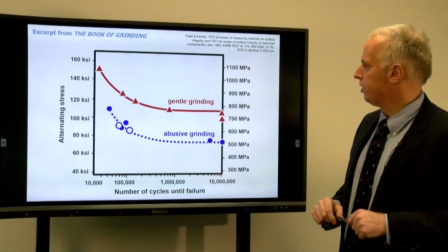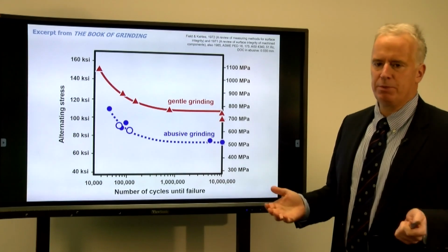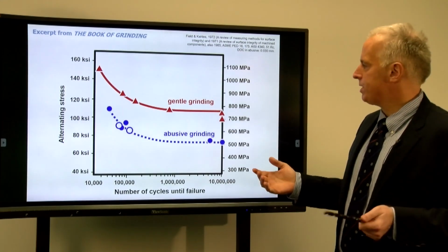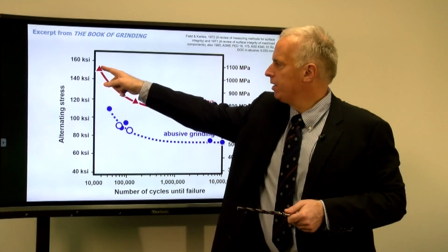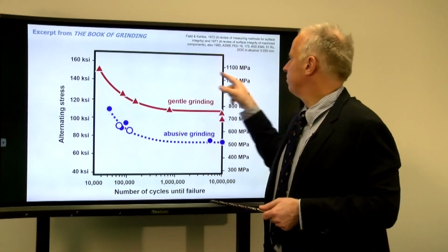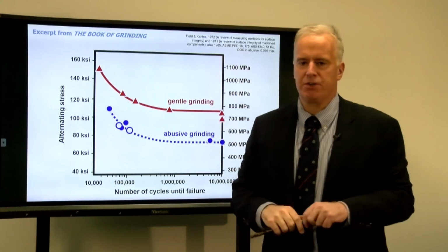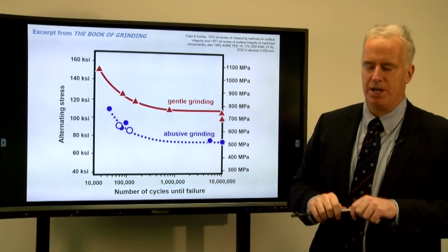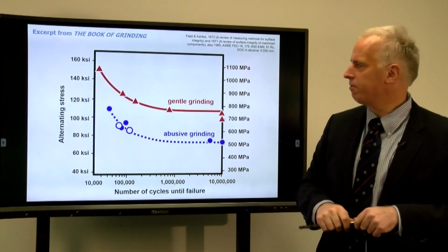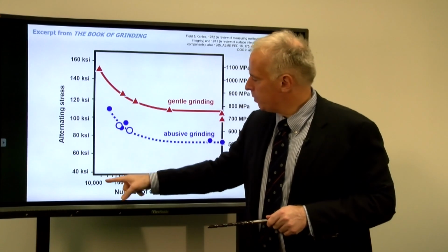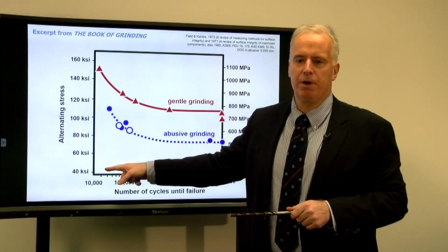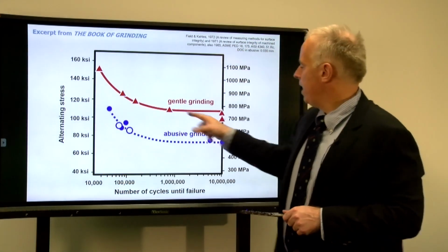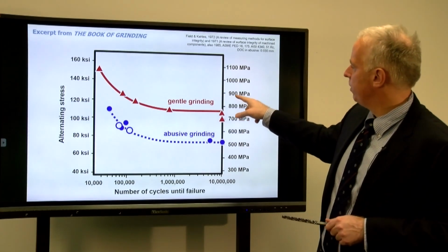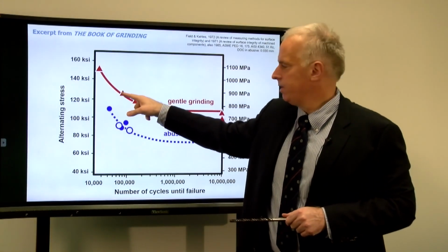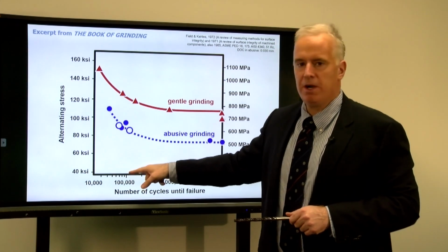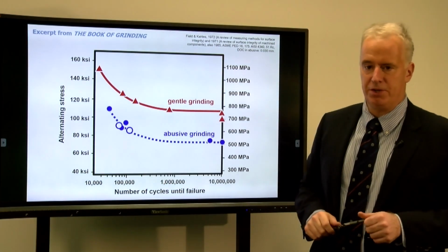Okay, so let's start with the red curve. So we grind a shaft, and then we say, okay, we are going to put a big load on it. So we're going to put 1100 megapascals of cyclic stress. It's not just a steady 1100, it's on, off, on, off, on, off. If we do that, we will get maybe 20,000 cycles before the guy breaks. If we put a lower stress, now let's say we only put 900 megapascals, now we're going to get maybe 100,000 cycles before the guy breaks.